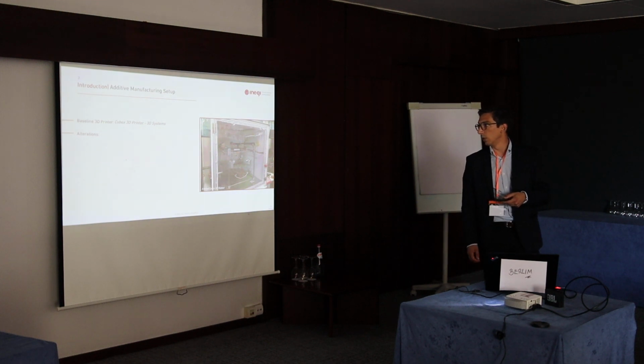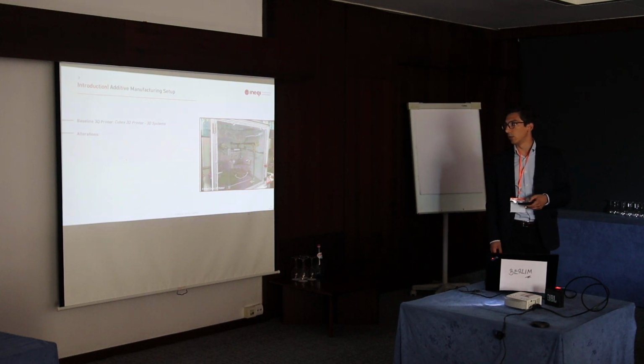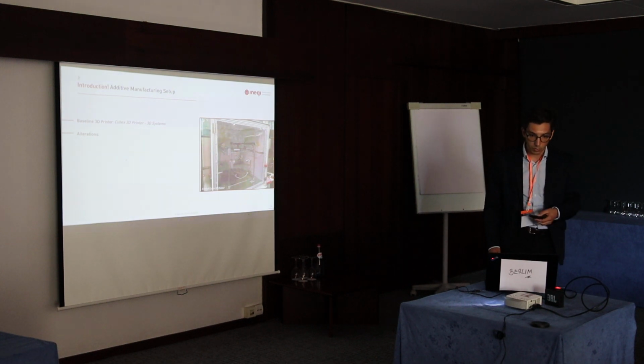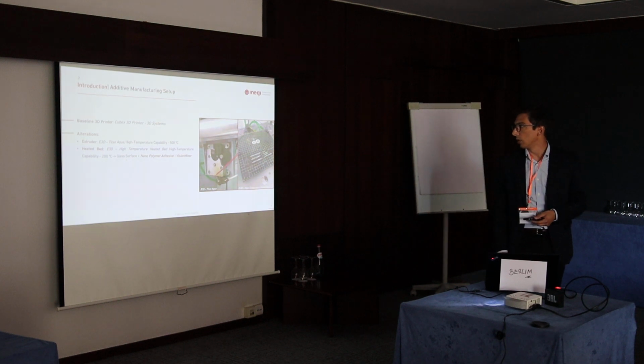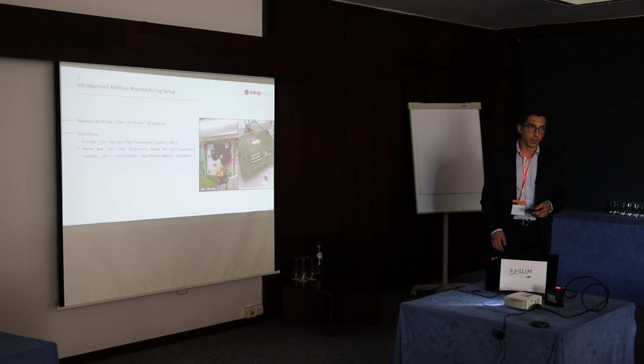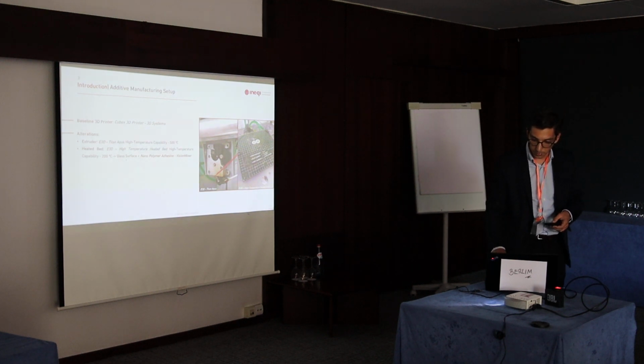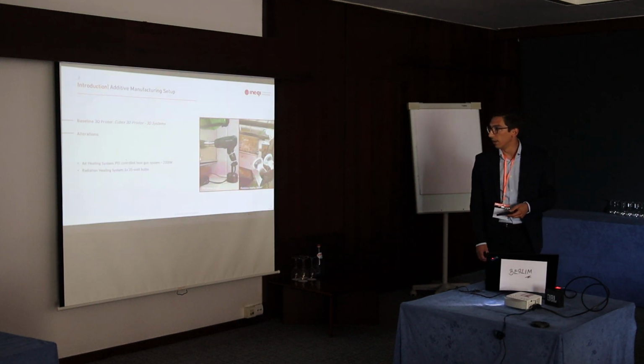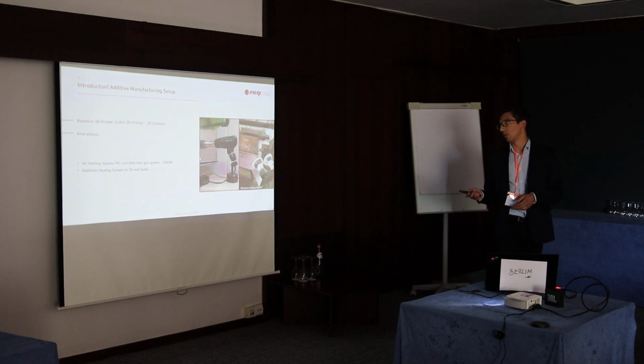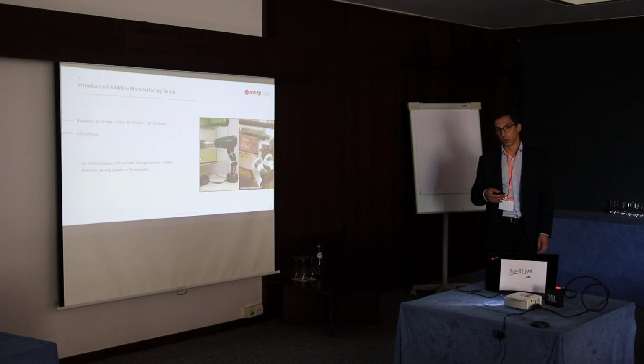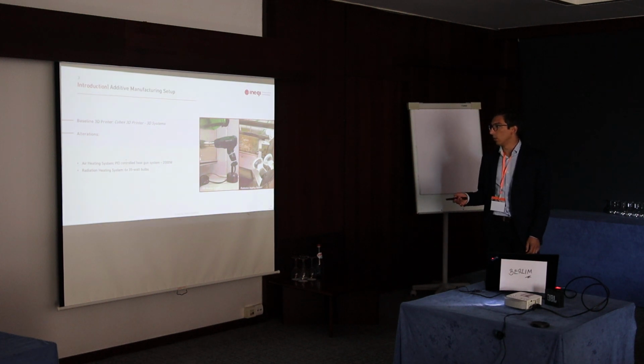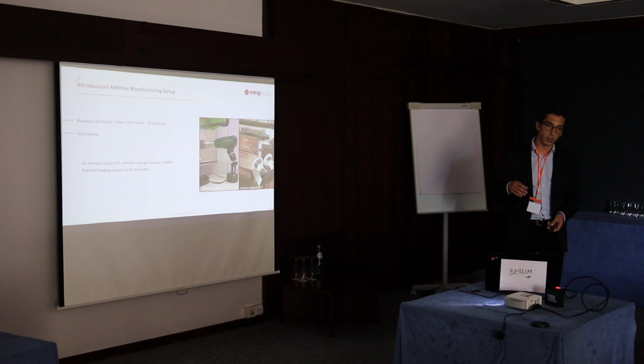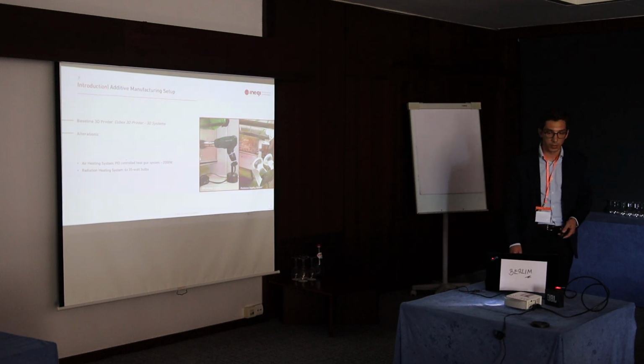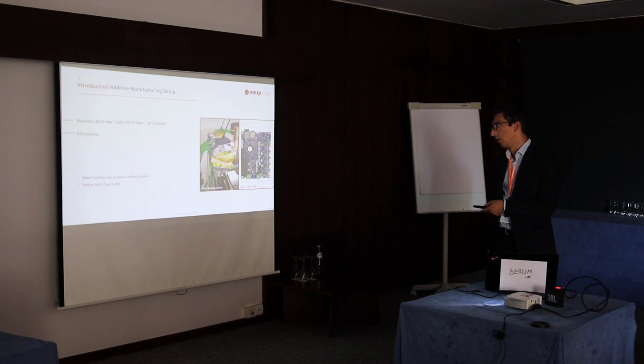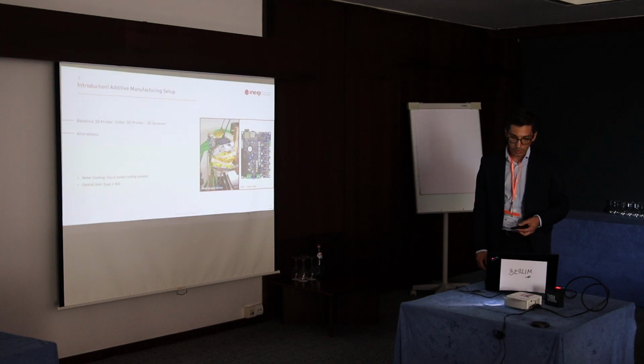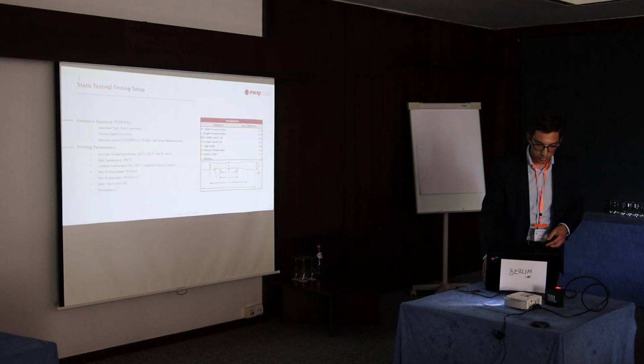In this case, we have kind of a homemade setup that we adapted from an existing printer, which is a CubeX 3D printer, to which we added an E3D extruder and heated bed specifically for high temperature plastics. We also developed an air environment heating system, in which you have a heat gun to push the temperature in the air up to 100, and then you have a radiation system that we estimate will increase the surface temperature by 30 degrees. And finally, we also have cooling for the motors and the control motor, but that shouldn't affect as much the producing of parts.